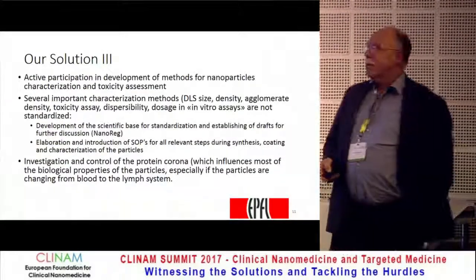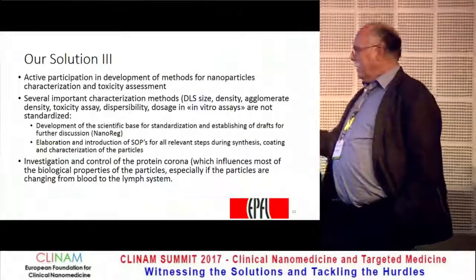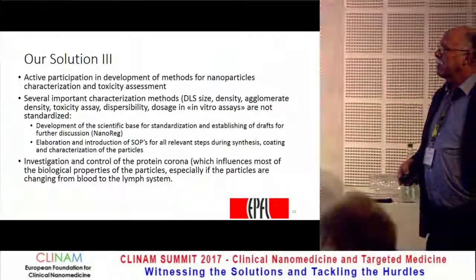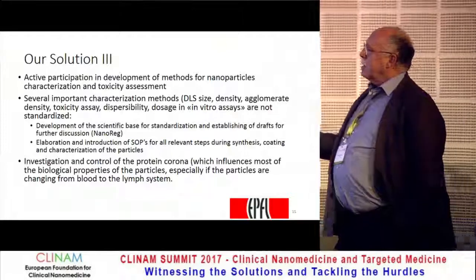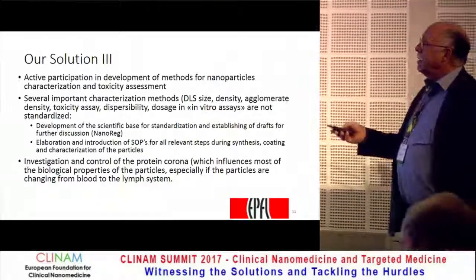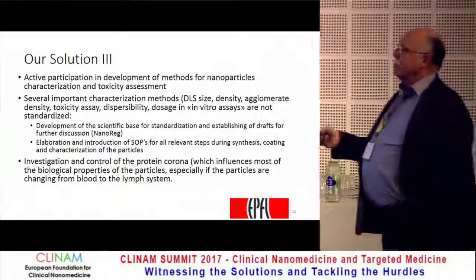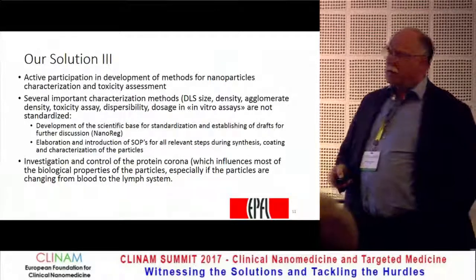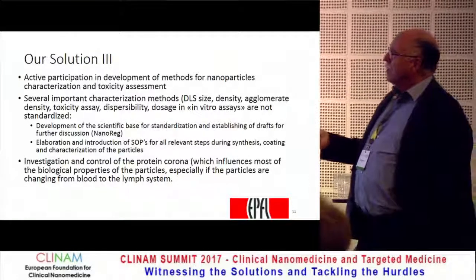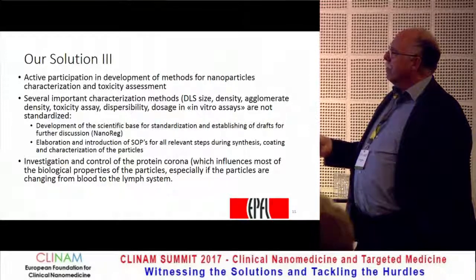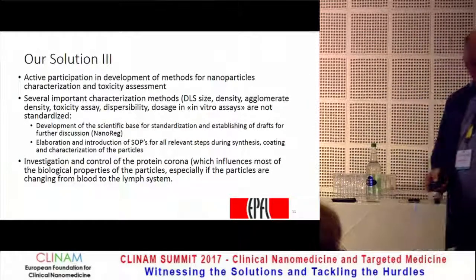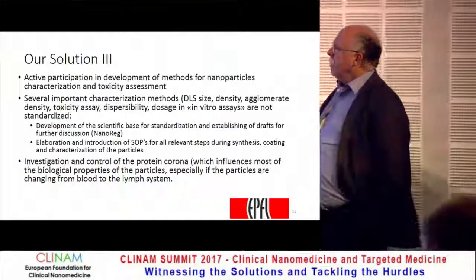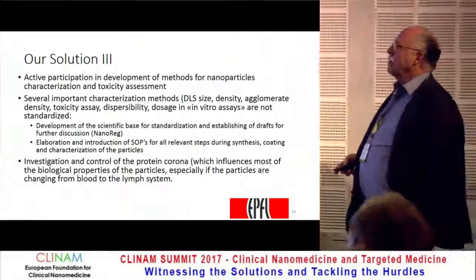Another important point is active participation in developing methods for nanoparticle characterization and toxicity assessment. Size measurement is not standardized, so we have to address density measurement, agglomerate density, toxicity assay, dispersibility, and dosage. We have worked on standardization of the physics and science behind these measurements, and several methods we have developed are now going to the OECD working group for further development of standards. We also have to do this work to get our lab results through to application.